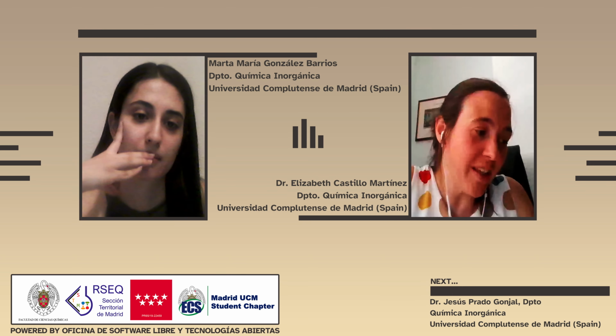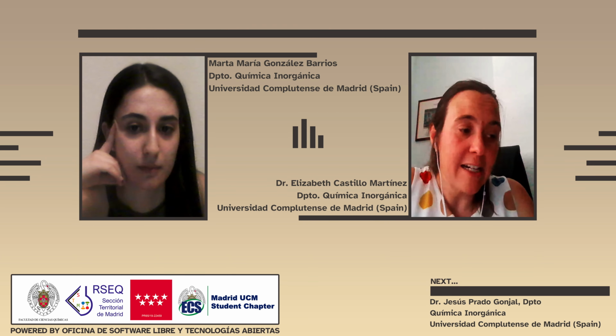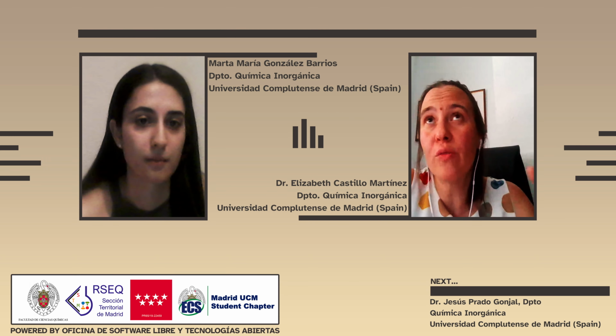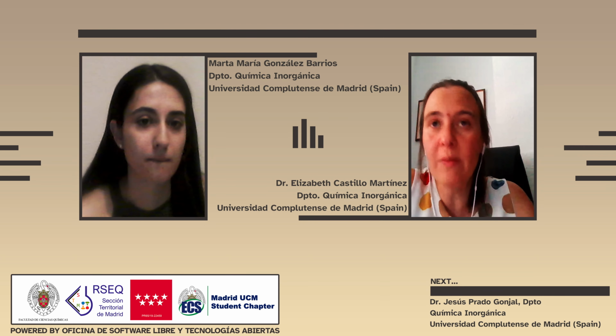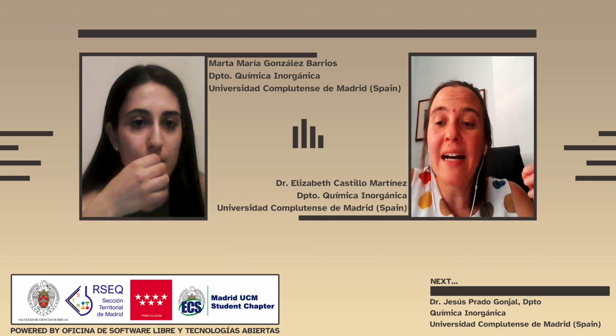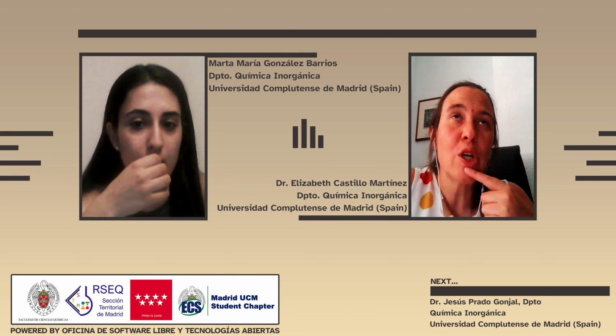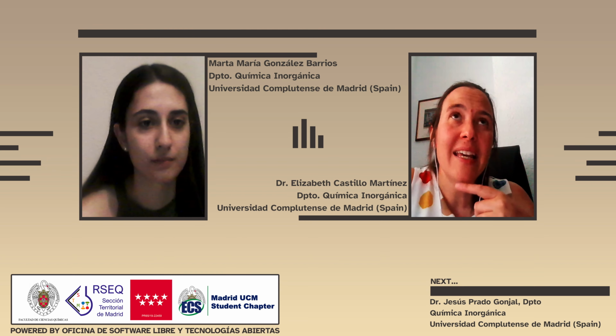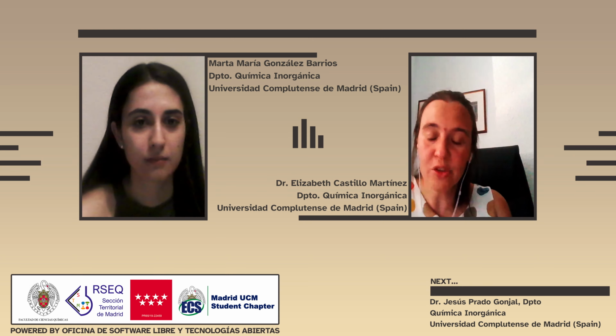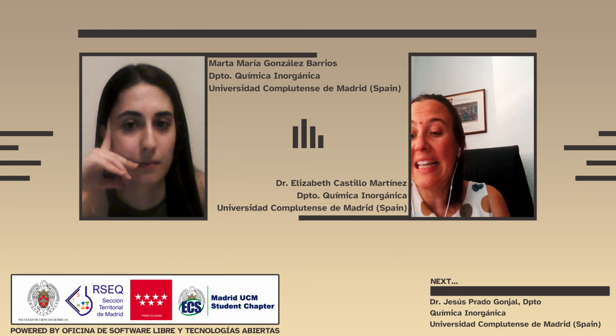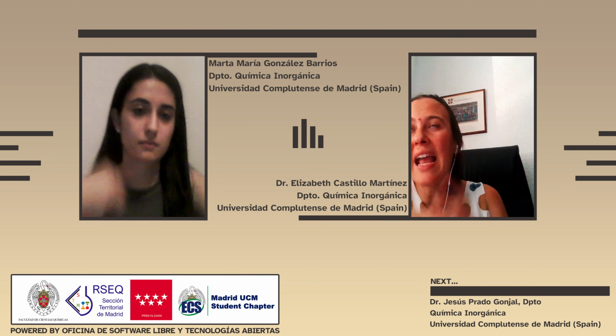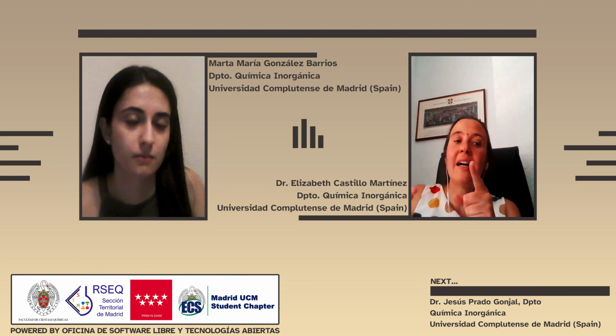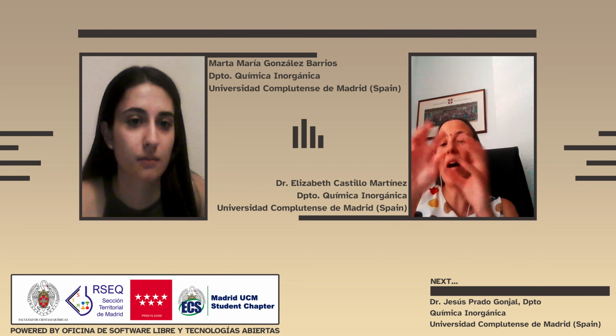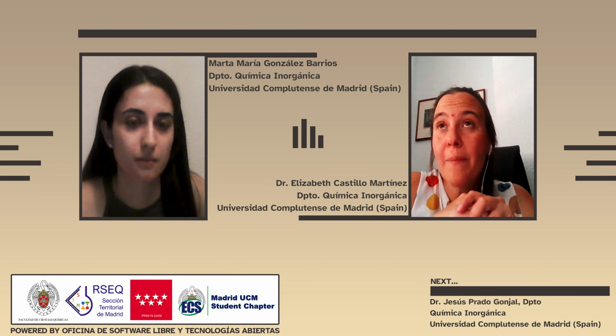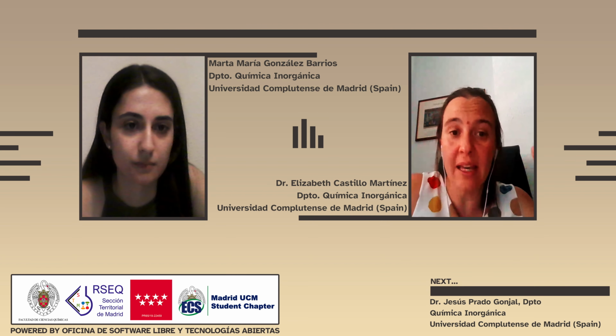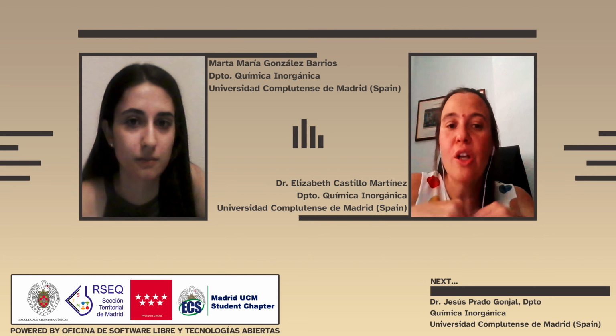Well, this is actually one of the issues with highly reactive alkali metals. As you go down from lithium to sodium to potassium, reactivity increases, and actually lithium metal is quite a good reference electrode, but sodium metal does not turn out to be a very good reference electrode. You can use the sodium metal as a counter electrode and as a source of sodium. But it is better if you can, of course, use another electrode which has, for example, a flat voltage plateau, and get this material in the middle of this plateau to act as a reference electrode. However, this electrode material must be a very good electronic conductor to be a good reference electrode. So it's not that easy.